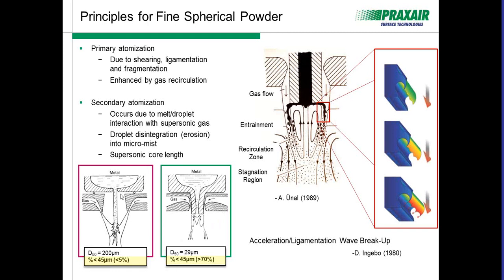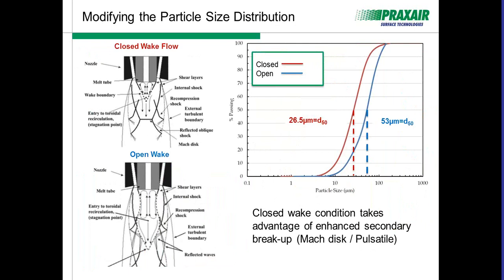The other technique is called free-fall atomization. And in free-fall atomization, you're only going to take advantage of primary atomization. Therefore, you're limited to only making coarse powders. And I'll show a distribution of that on the next slide or two. When we think about close-coupled atomization, remember that means that the liquid is immediately impinged upon by the gas. There's two different styles or types of close-coupled atomization.